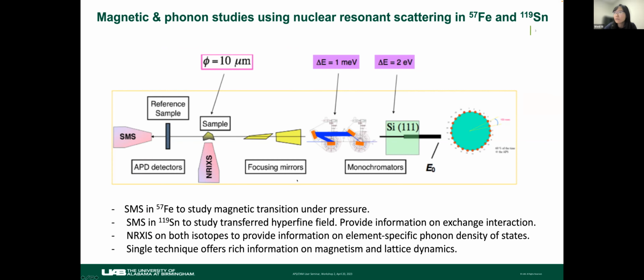I think most of us are familiar with this setup here. I just want to mention that we have done this experiment at sector 3 and sector 30. Sector 3 on iron 57, and tin 119 at sector 30 with Michael. With this single technique, we can get the information on the magnetism on iron, and also look at the transferred field on the tin side. We can also collect the NRIXS data, and get information on the element specific phonon density of states.